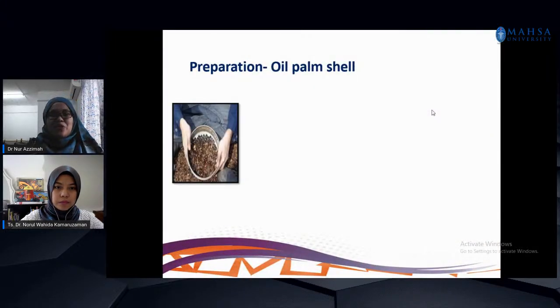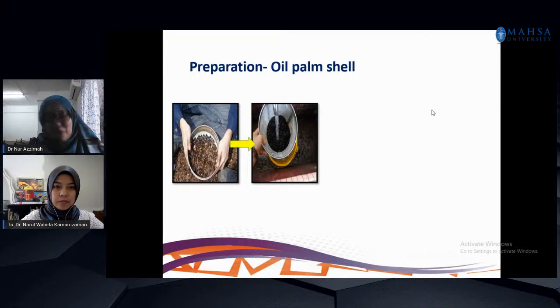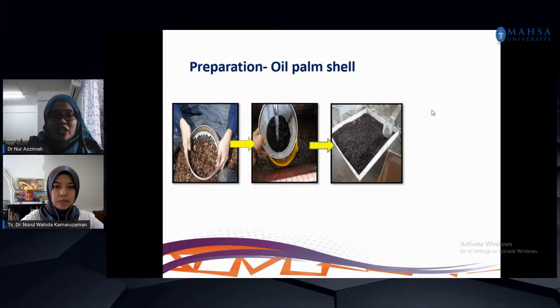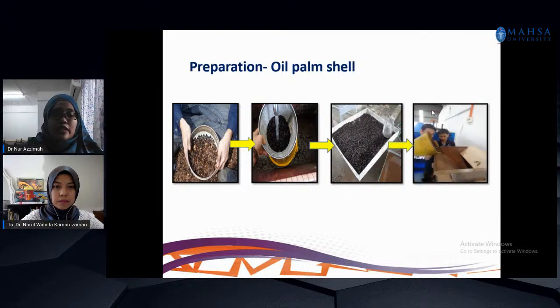And also, if you want to use this oil palm shell, you cannot simply take it and replace it inside the concrete. You have to do some processing. Upon taking the sample from the factory, first you have to wash the oil palm shell, because we know that this is an organic material. So sometimes there will be impurities, sometimes there are some insects, so you have to wash it first. After that you have to dry it until it reaches SSD, which is saturated surface dry condition. After that you have to crush it using the jaw crusher, until certain sizes have been achieved, right? Then only you can use it inside your concrete, right?